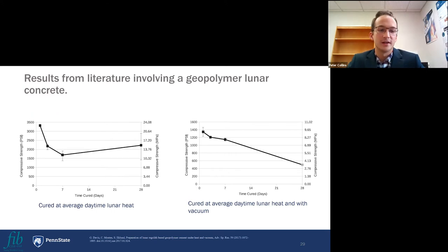On the left is their low solution geopolymer concrete cured at the average daytime lunar heat, which I believe they did 110 degrees Celsius. And you can see it goes from about 3250 PSI or 21 megapascals and starts to drop off. And the error bars get quite a bit larger too as time goes on. So the heat does have an influence on the compressive strength of these. When you combine the heat with the vacuum, you start to get a significant drop in your overall compressive strength. You started again around maybe 1400 PSI, which is significantly lower than when you have just the heat, right? We started with around 3250 there, and then it drops clear off down to about 500 PSI at 28 days. So the durability aspect of these is a large issue.